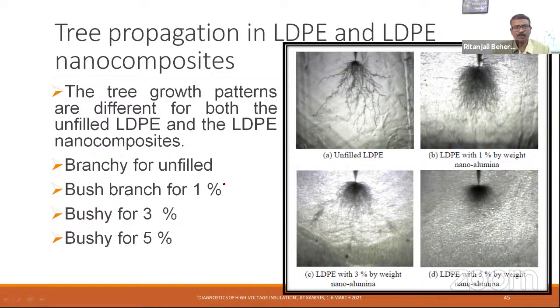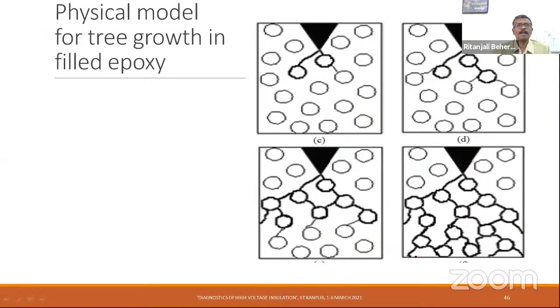It is becoming more branchy than for an unfilled LDPE. With 1% filled LDPE, we can see a kind of bush branch, and with 3%, it is more bushy with small branches, and with 5%, it becomes completely bushy.